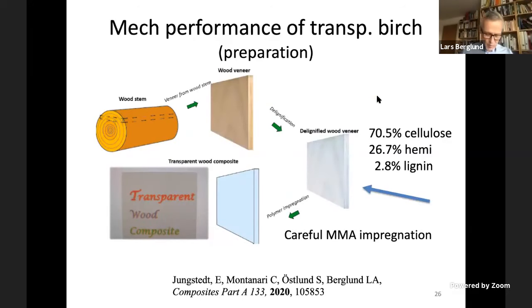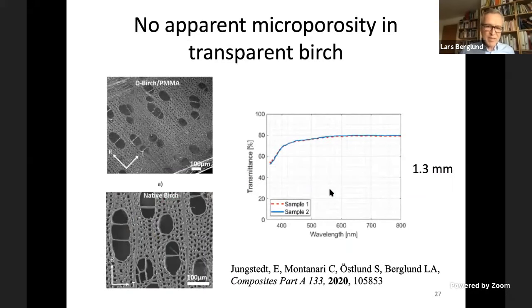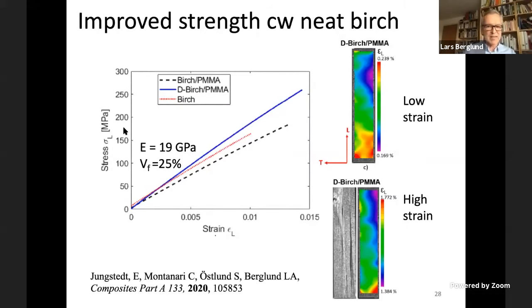I wanted to say something also about mechanical properties. This is Jungstedt's work. Delignified veneer is actually a very interesting component for many applications. If you impregnate them with PMMA and you do it very carefully, you basically fill all the porosity. This is birch, but even the lumen in small birch fibers are completely filled. And the question is, what kind of properties can we then get? And we can really improve strength compared with neat birch.